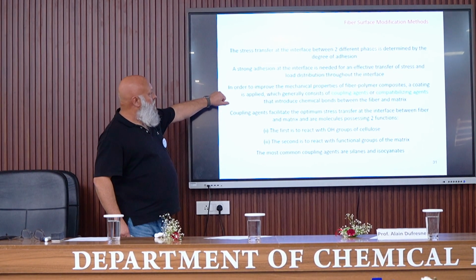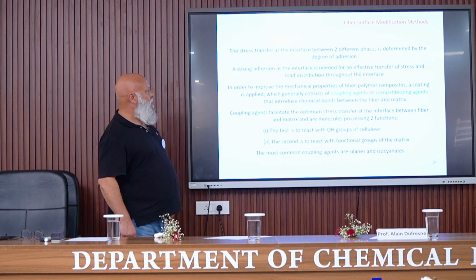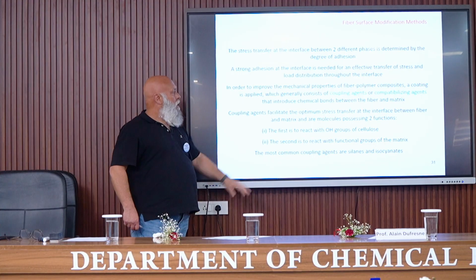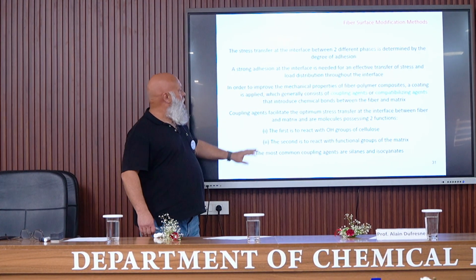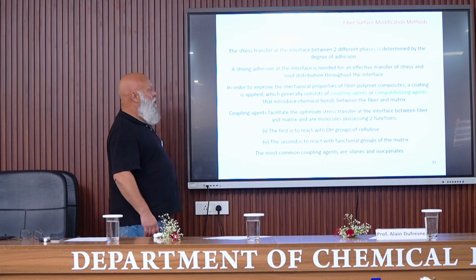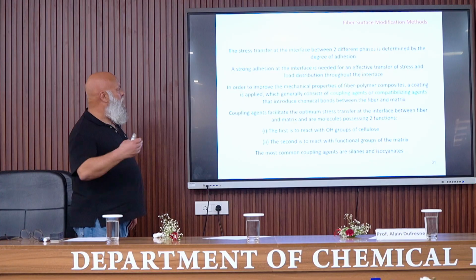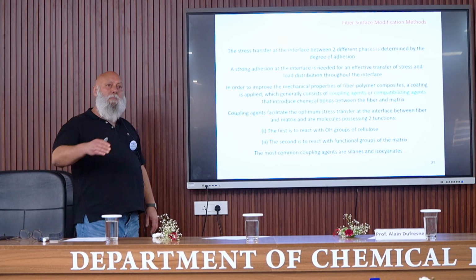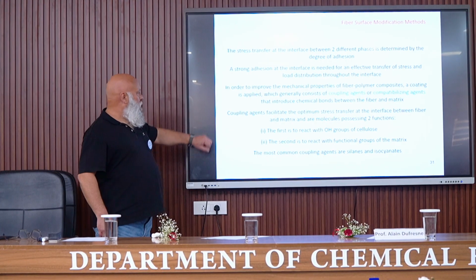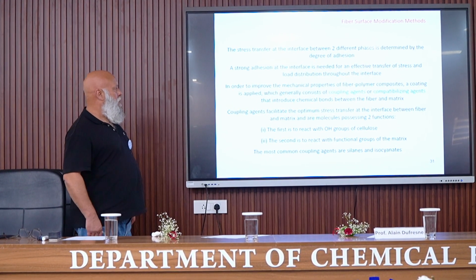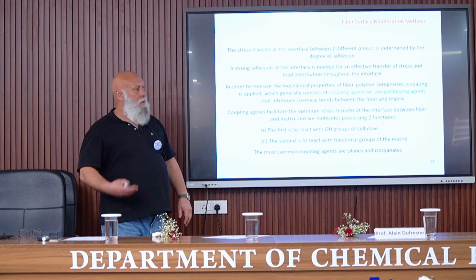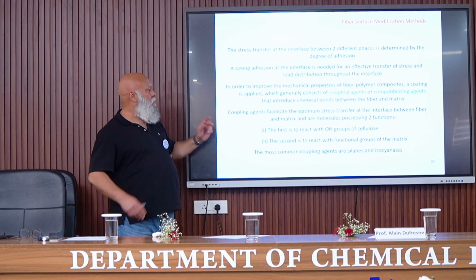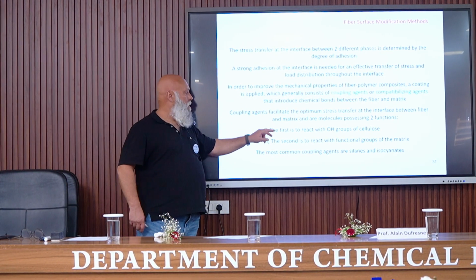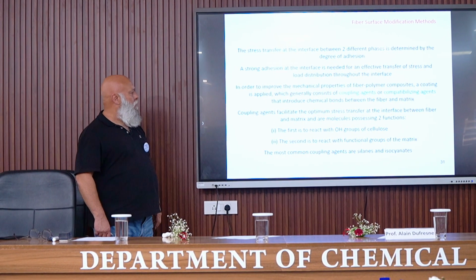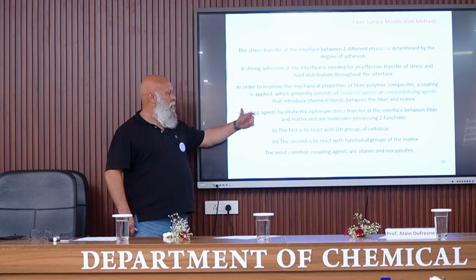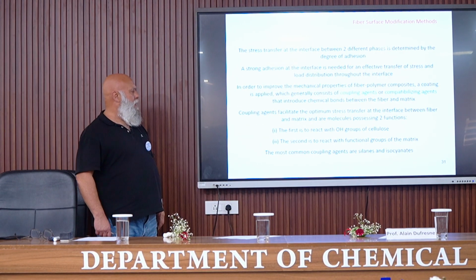So this strong adhesion is necessary, and to improve the mechanical properties of the composite, a coating is applied. Generally, so there are different options, but generally it consists of coupling agent or compatibilizing agent that introduce chemical bonds between the fiber and the matrix. It can be also physical bonds. So this coupling agent facilitates the optimum stress transfer at the interface, and this compatibilizing agent needs to have two functions. The first one, that will be able to react with the OH groups from cellulose, and the second one that will react with the functional groups from the matrix.